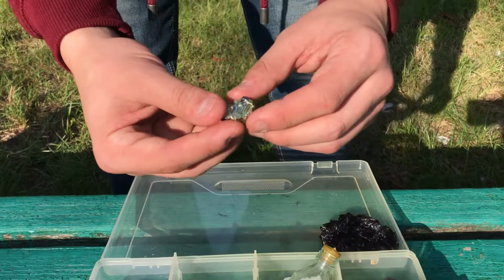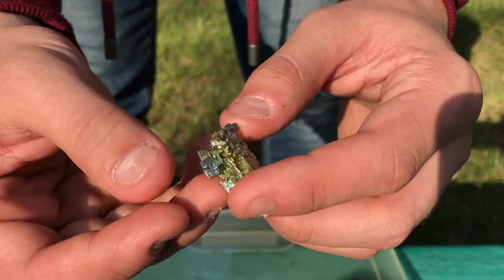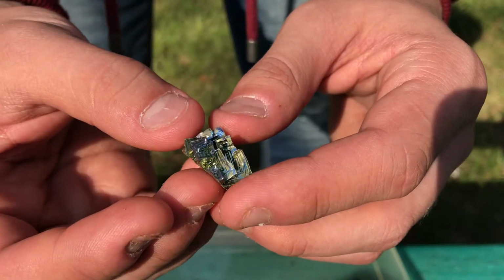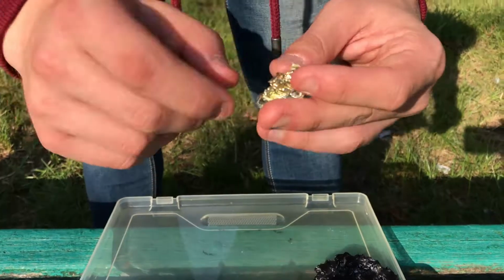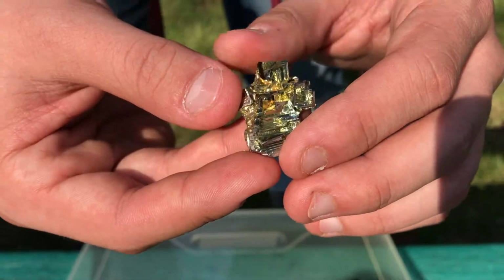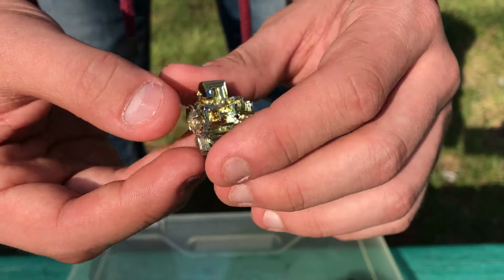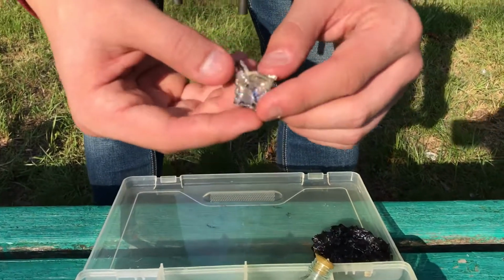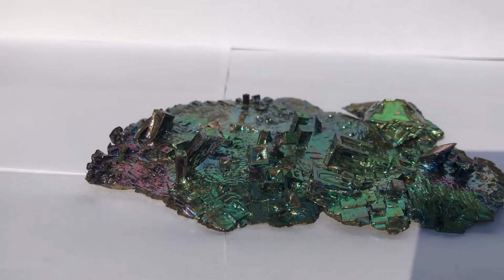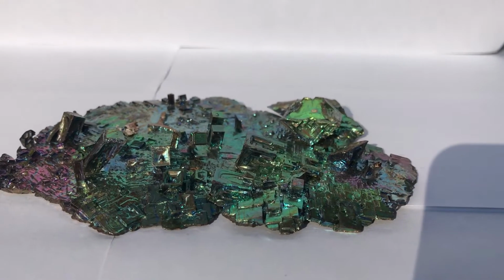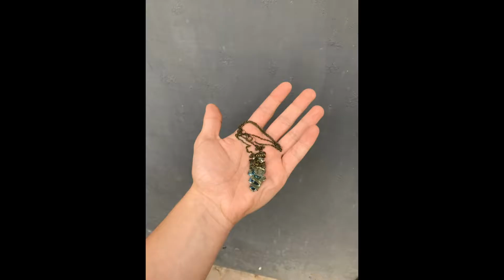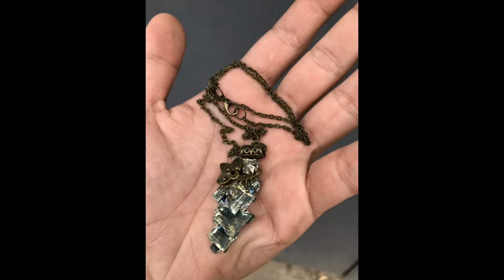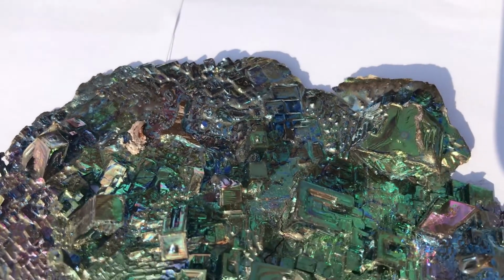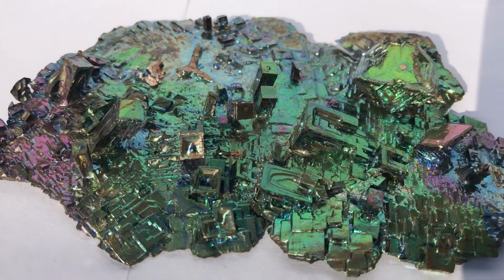Bismuth's surprising property is that it starts to form beautiful crystals during solidification. The size and shape of the crystals will be dependent on the solidification rate, as well as the presence of impurities. The slower the cooling, the higher and more beautiful crystals will be obtained. The crystals I have obtained are not very big, however, with a beautiful oxide film. These are just good looking, but they have no practical use. However, I make necklaces from them and then sell them like this one. I also have obtained some kind of an improvised post-apocalyptic town from the formed crystals.